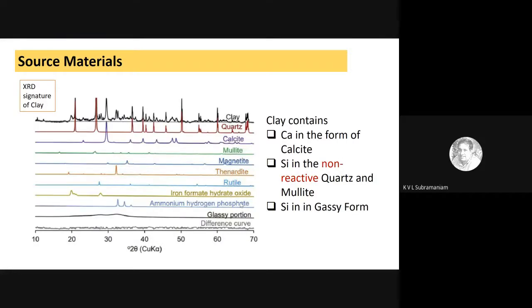The other material is clay. So we did the X-ray diffraction of clay, and we found that while clay contains silica, a lot of it is in the form of quartz. And if you remember, quartz is a very inert form of silica. So this is not of use to me, but it can't be helped because this is low-grade clay which contains silica in the form of quartz, which will be non-reactive. So I have to now see what is the silica that this clay brings in the reactive form. And that is given by this line shown here at the very bottom, which is shown as the glassy portion. This is that silica that is available in the glassy portion.